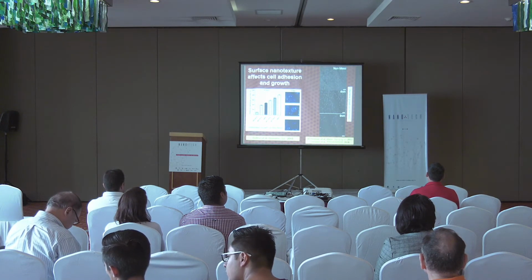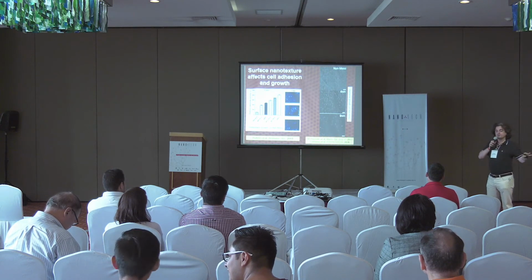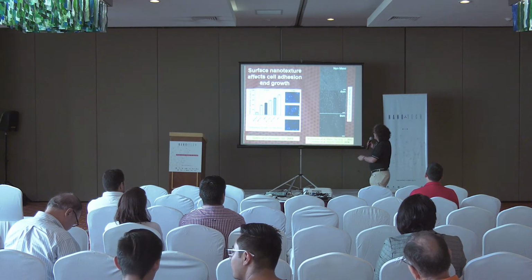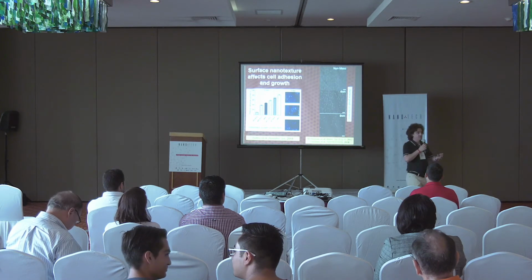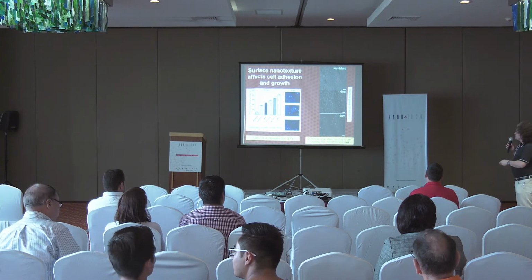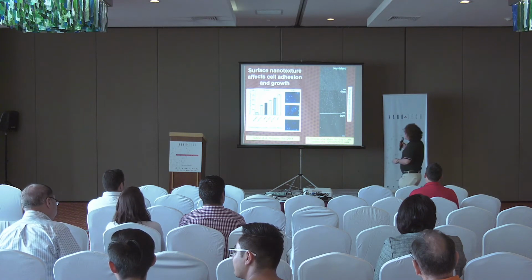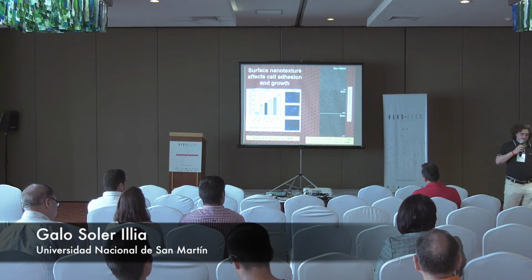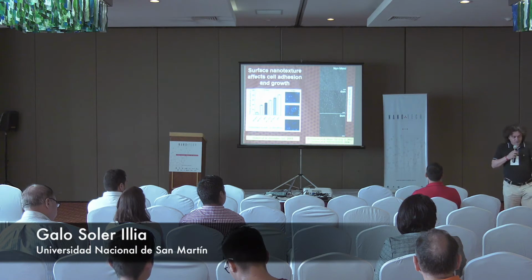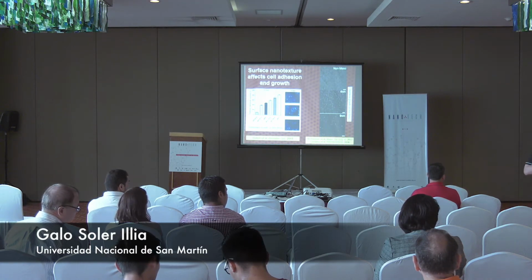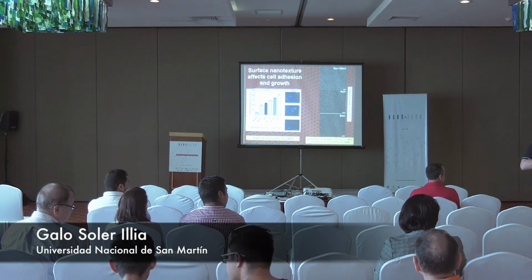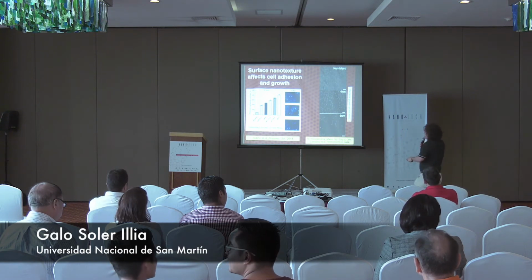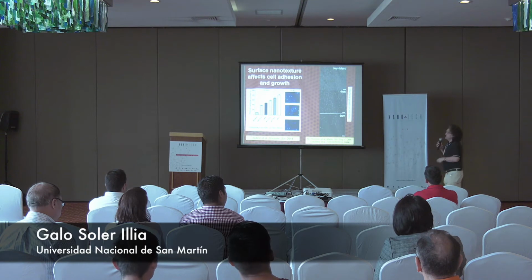What we found was much more interesting just with the blank experiment. Without putting anything in the pores, we found out that the growth and proliferation of cells, osteoblast cells, which are the cells that eventually form bone, significantly changed by changing the porosity. This means that cells look at the floor, and if the floor has a pattern, like the floor here, the cells are not so sure to grow there. Porosity influences cell growth. We saw this also with bacteria.